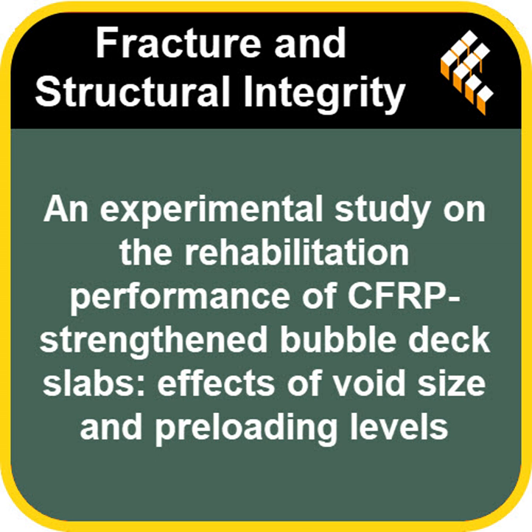Ah, okay. If we connect this to the bigger picture, it signifies that the bond interface, that connection between the CFRP and the concrete, not the concrete strength or the steel reinforcement itself, was the limiting factor. It determined the ultimate performance. So the system failed at the glue line, essentially. Right. The repair system was failing at its adhesion point, not necessarily the materials themselves breaking. That's a fascinating insight. If the bond is the weakest link, does that suggest there's a limit to how much CFRP can actually achieve, regardless of the slab's initial damage level? It absolutely does.